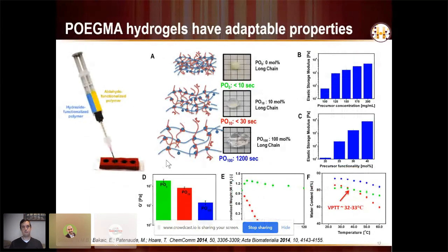So just very briefly, there's citations here if you want to know more details, but we've shown that these POEGMA hydrogels can have really highly adaptable properties. They can be thermoresponsive, they can be not. They can be transparent or not. We can tune the elastic modulus over 2 to 3 orders of magnitude. We can introduce thermal responses at particular temperatures, whatever we desire. And we can control the degradation time from very fast to very, very slow.